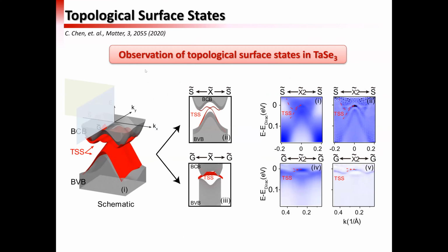So that's why we turned to do the measurement using the laser light source. The laser light source has the advantage of a very small beam spot that we can control, and also it has a very high energy resolution, and also because it's low energy, it also has a very high momentum resolution compared to the synchrotron ARPES measurement.